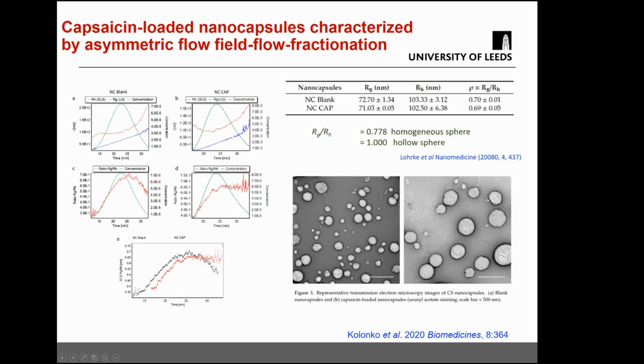Also, the comparison between the two radii informs about the shape of objects. In the case of these spheres, we normally see them as spheres on the TEM, transmission electron microscopy. However, the ratio between them is slightly lower than what we would expect for a homogeneous sphere, and we can see that they're slightly elliptical. So it's a very powerful way to infer the morphology of polymers, but also of particles.